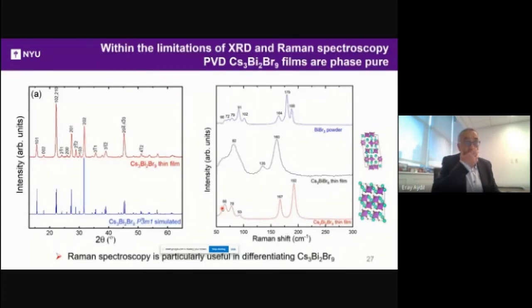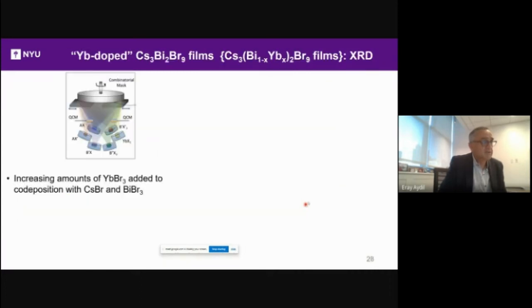Okay. So I wanted to convince you that, within the limitations of X-ray diffraction and Raman spectroscopy, the films that we make using this solid physical vapor deposition technique are phase pure. This is the simulated X-ray diffraction, and this is the thin film. All the peaks match. There is some texturing, and the Raman shows that it is phase pure, and when we compare it with potential impurities, we don't see anything in our thin film. So we're confident that our optical absorption and photoluminescence is correct.